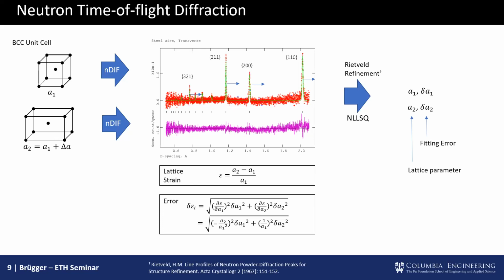Here, the beauty is if you have a residual stress, for example due to plastic deformation in an area of your system, that creates some incompatibility, so that during unloading you get a partial hysteresis loop. Then what you can measure in the end is the residual elastic strains left in the material, irrespective of what plastic flow happened in that material. So you get a very clean understanding of the actual strain potential in the material. If you cut the sample, you would see that deformation spring back, if you're just doing traditional slicing.